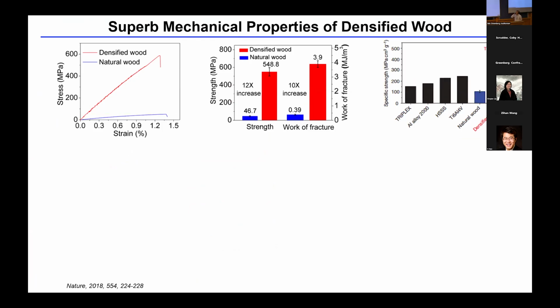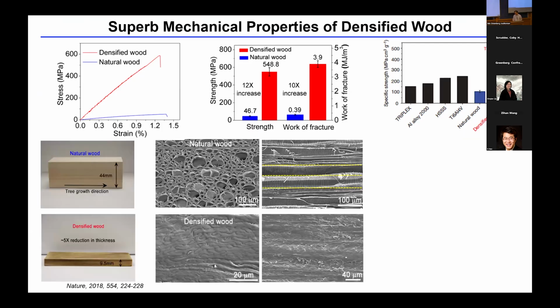So these are some of the data, and I think I've talked about them at different conferences as well. One of the highlights is that as we increase the tensile strength, we don't lose the ductility. But if you normalize by the weight, we always say this material is as strong as steel, at least in one direction, but it's 6 times lighter. Right? So if you normalize by the density, you can actually get a much better so-called specific mechanical strength.